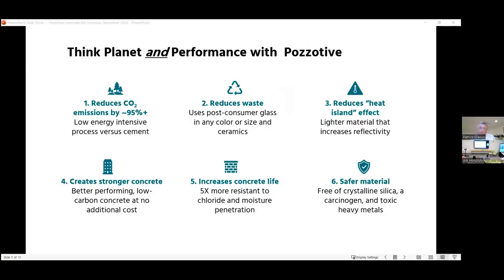This kind of captures really our story a little bit. We like to say think planet performance with Pozzotive for all of these reasons. One, it's got a carbon footprint that's only about 5% of the cement that it's replacing. So it's almost a ton for ton savings for every ton of cement that can be replaced with a ground glass Pozzolan. It can use any color, any size glass.